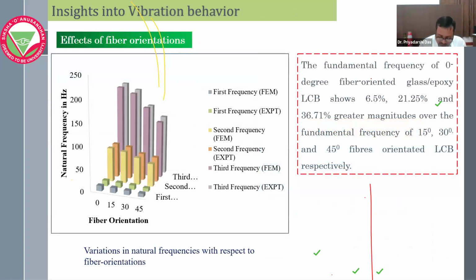So we have calculated the effect of fiber orientation. The fundamental frequency for the 0 degree fiber orientation, obviously, is more than the other orientations, that is 15 degrees, 30 degrees, and 45 degrees. That means whatever the fiber orientation, we need the 0 degree fiber orientation, because it will give the maximum frequency compared to the other fiber orientations.